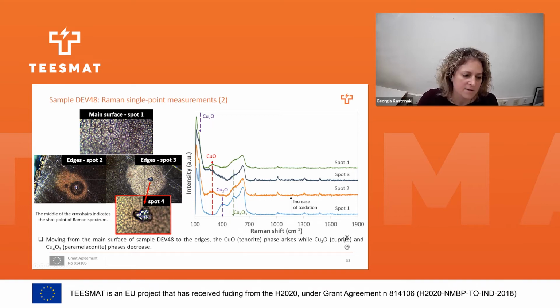So from, let's say, a non-problematic region, and at this point, and then at this point, which is closer to the circle, and finally at the source. And we compare them here. So you can see that this is, let's say, less oxidation, the lower oxidation state of copper. And as we move further to the spot, we see that this is decreasing. So it's higher for the fresh state.